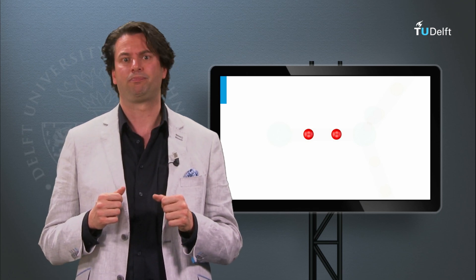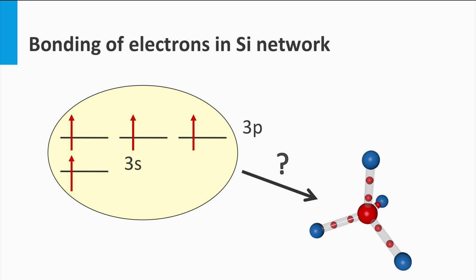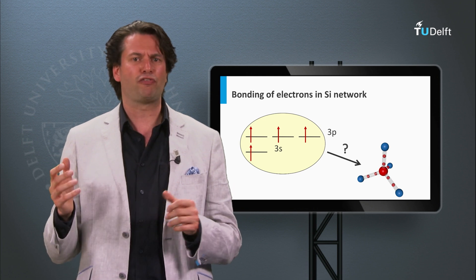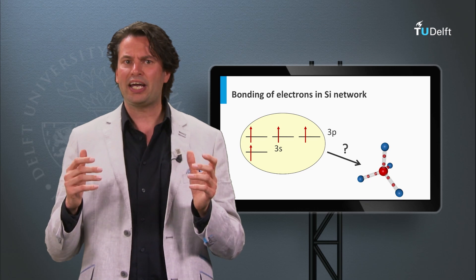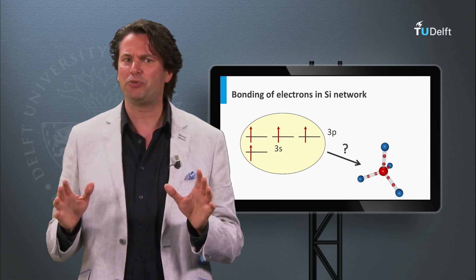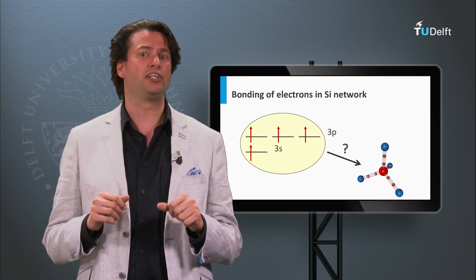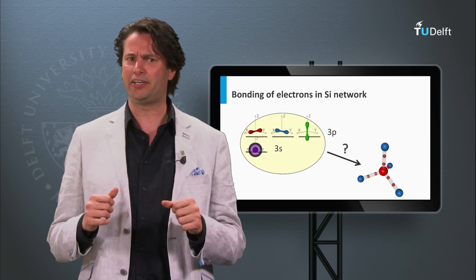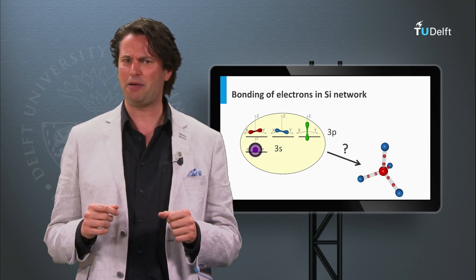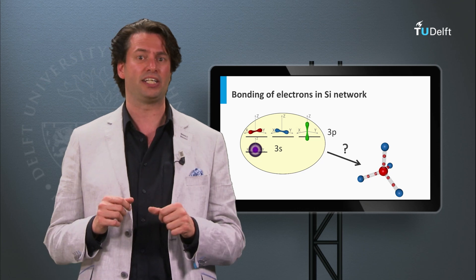The resulting orbital is called a molecular orbital. From nature we know that the orientation of a silicon bond is tetrahedral-like. Consider the lattice of crystalline silicon, which is a diamond cubic crystalline lattice. Looking at a single atom in such a lattice, the angle between all four bonds is 109 degrees. However, if we look at the orbitals of the four valence electrons in the third shell of silicon, we don't recognize the tetrahedral coordination — their shapes do not match a tetrahedral coordination at all.